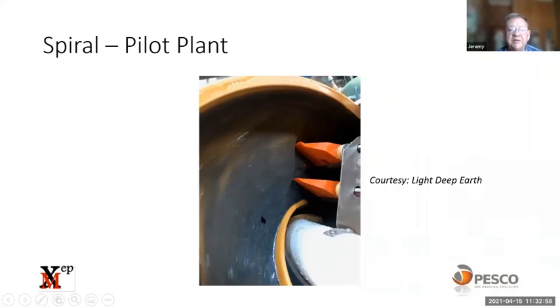So the concentrate, the heavy stuff, moves towards the center of the spiral. You can see it's nice and dark. And then you take a cut, that'll be your concentrate. The middlings contain some iron ore and some unliberated particles that you take out the middle. And then the tailings is normally your light stuff, your silica, fine silica, and so on. And that moves to the outside.